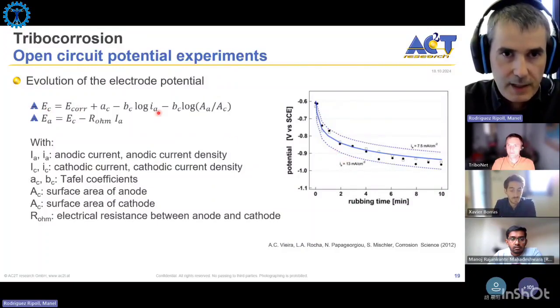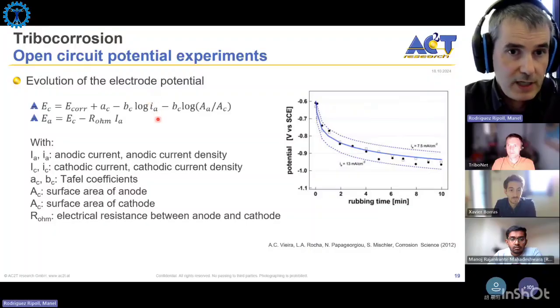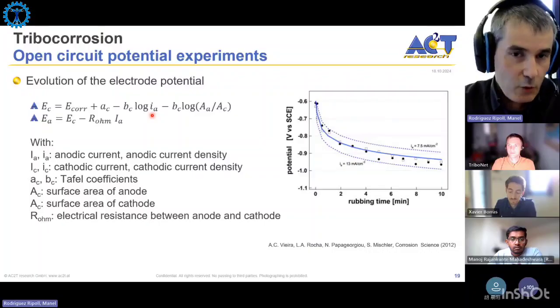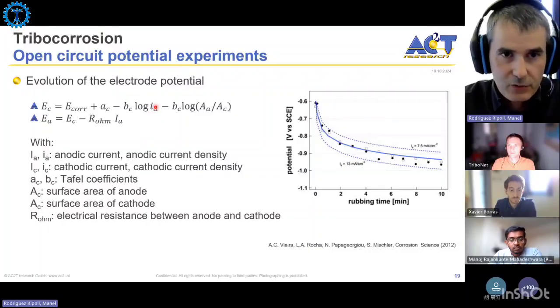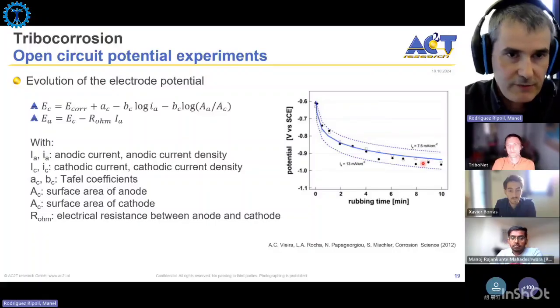And the only parameter that here you wouldn't know is the anodic current, the anodic current required, or triggered every cycle for repassivating the worn area. So you can track or calculate or estimate this anodic current density by plotting, for example, this data. So this is a quantitative model.